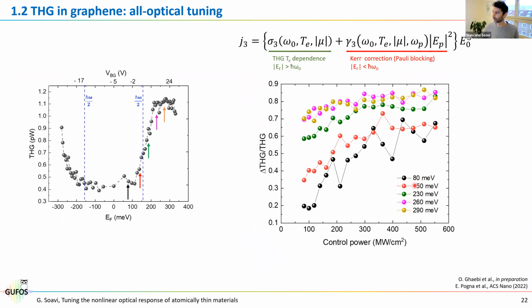When you look at small values of the doping and you change the control power, so the fluence of the control pulse, then you see that the black and the red curve, so let's say here, small values of the doping, increase linearly, or almost linearly at least, with the control power. And this is a good indication that the modulation of the third harmonic is dominated by Pauli blocking rather than electronic temperature. But as you increase the Fermi level, so you go to these values, you see that the third harmonic modulation is almost saturated, even for very low values of the control fluence. And this is a good indication of a highly nonlinear process that could be explained simply by electronic temperature effects.